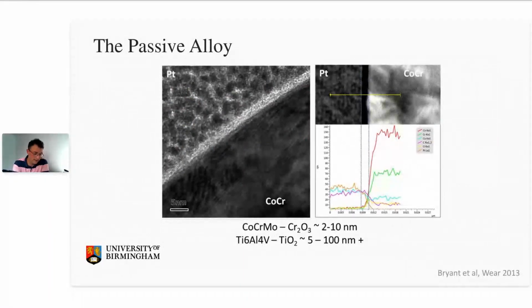But as I mentioned, this is ultimately the crux of what we're talking about, the performance of these materials. So this is a TEM image of a passive film that's formed on a piece of low carbon cobalt chrome, and this is ultimately the barrier that protects the very reactive cobalt chrome surface from the external environment. And when this is subject to stress and fretting and various other mechanical perturbations, this layer can become cracked. Stress in itself can drive the corrosion reactions across that interface, and ultimately we have rapid oxidation of that subsurface. So as well as corrosion, mechanical damage at these interfaces will cause damage to this film, and ultimately this gives rise to this mechanism of tribocorrosion, but also fretting corrosion, which we'll talk about in a bit more detail.